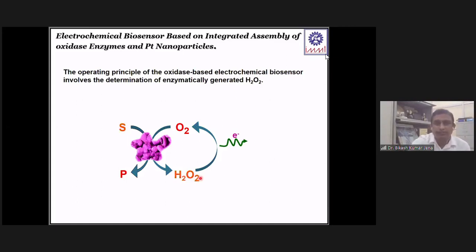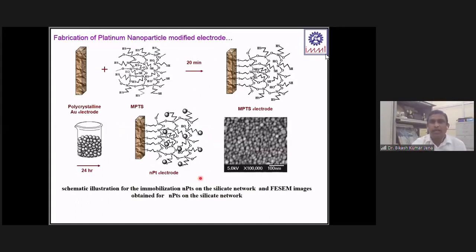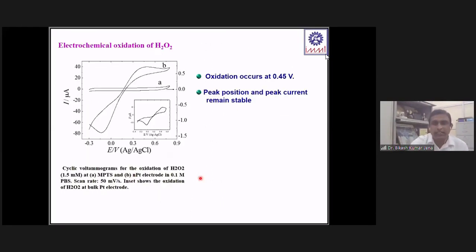So what we did, we have tried to develop some kind of platinum nanoparticle modified electrode, because we have observed that this platinum nanoparticle modified electrode is sensitive towards hydrogen peroxide, and that can detect hydrogen peroxide very easily. So we checked with this platinum nanoparticle modified electrode. In a similar way, we have developed platinum nanoparticles on the electrode surface. Here you use the platinum nanoparticle modified electrode. You can see how this nanoparticle is modified on the electrode surface. And this image justifies and proves that the nanoparticle is there on the electrode surface.